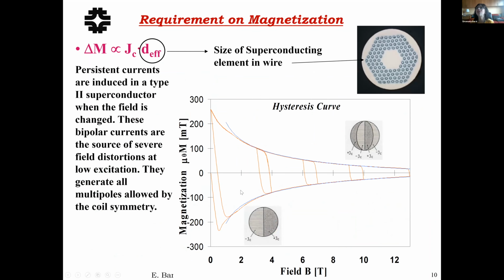And then another very important feature of magnets is that the superconductor magnetizes, and in the opposite way that iron does. It's a diamagnetic material. So you can see that when you put it in a magnetic field, it has its own magnetization curve. This is due to the fact that each one of these superconducting sub-elements magnetizes, and it generates these two opposite currents in the filaments that go along and come back, and this is why we have the magnetization curve. And as you can imagine, this creates a lot of trouble for the magnetic field quality in the magnets, but also, and that's what we found out, it creates magnetic instability, which I'm going to show you later.